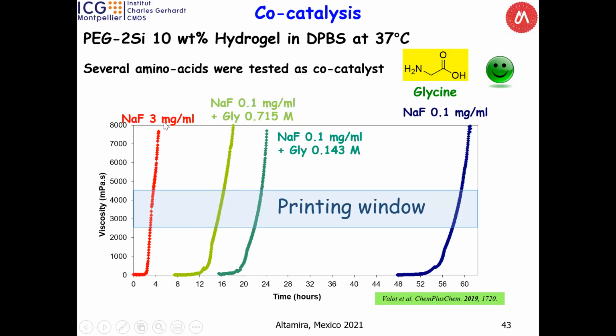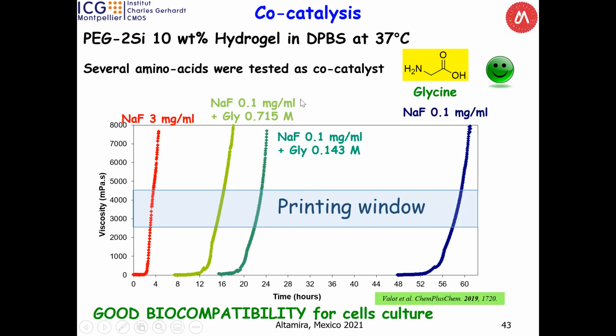So I summarize here: sodium fluoride alone, 3 milligrams, very fast but toxic; very low, but not toxic. And we find several possibilities to manage the printing window, here or here or here. I select only two by adding 0.1 milligrams of NaF and glycine at 0.7 molar. Okay, it's possible to get your gel after 14 hours. So you prepare it, for example today at 7 o'clock in the afternoon, and you come next day, you can print it. The idea is to find the printing window.